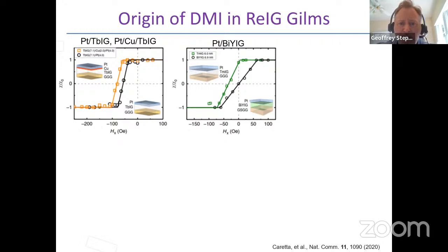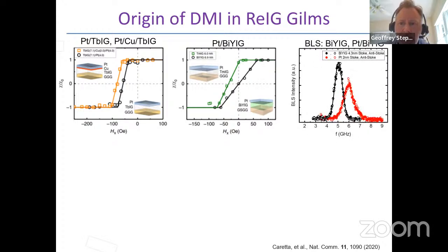And likewise in these materials, because you can make garnets with a variety of rare earths and you can make garnets without a rare earth, we've looked at the role of the rare earth itself in the garnet, because again, you need a broken inversion symmetry and you need a strong spin orbit coupling. And what we found is that if we remove the rare earth and instead put in bismuth, which allows you to still get a PMA, the DMI vanishes. And we find the same kind of behavior using BLS. So whether or not we have a metal layer on top of a garnet, if the garnet does not contain a rare earth element, we find no evidence of DMI.